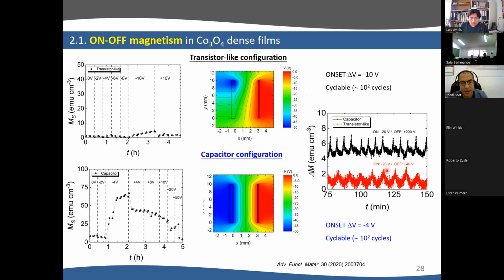In both cases, nevertheless, we have good cyclability. We can induce these on-off transitions many times. Here, this black curve is shifted for clarity, but it should be at 0. This is artificially moved upwards to compare the two, but it is between 0 and something. We are generating this magnetic signal and removing it. And for the capacitor, minus 4 volt is enough. For the transistor, we need minus 10 volt.